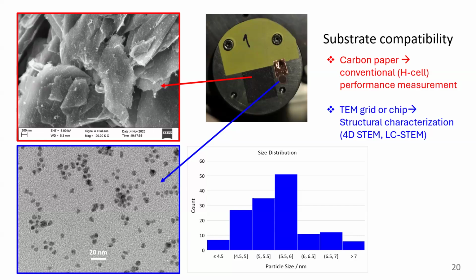And then on the other hand, for structural characterization, things are deposited on TEM grids, so that you can determine the physical structure of the catalyst in terms of morphology, composition, etc. And as I mentioned, since there's a quadrupole mass analyzer, we can control the particle size distribution during the synthesis.